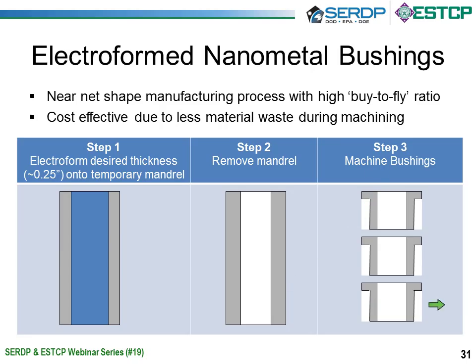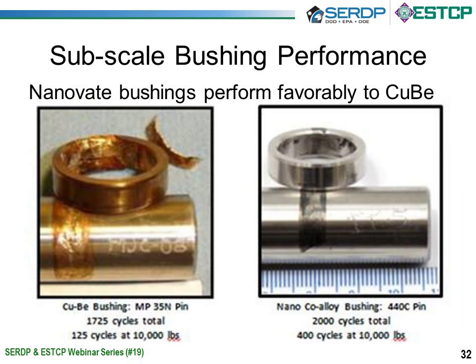Resulting in little waste because you just remove what's on the outside, an effective process. And here's an example of a picture of the subscale bushing test that we performed. On the left, it shows the copper beryllium bushing with a steel pin. And on the right, it shows the nano cobalt alloy bushing with a steel pin. So this test involves loading the sample, loading the pin in the sample.